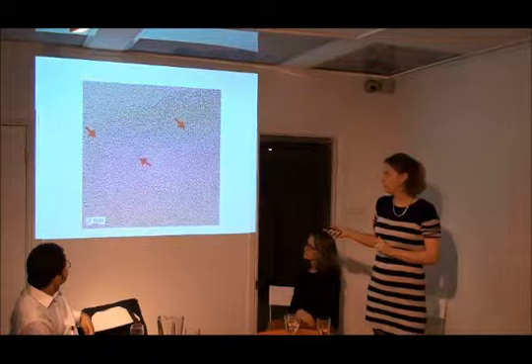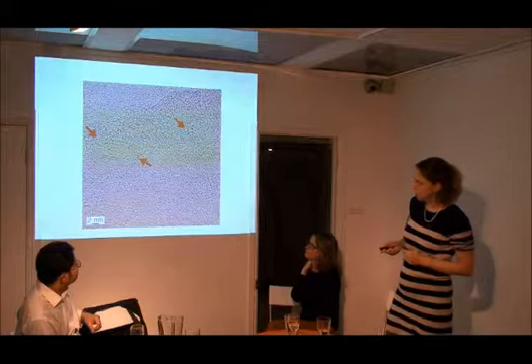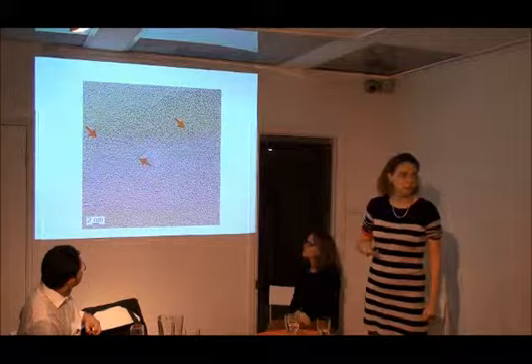In addition, when you shorten the length of the tubes, the way that you do this is to use a very strong oxidation treatment, and that actually damages the nanotubes. And so what we've found then, when you expose these to the cells, the structure breaks down entirely. This used to be a multi-walled nanotube, a fibrous multi-walled nanotube, but now you can just see these remnants of the tube inside the tissue, and that's implying that it's breaking down in the tissues.